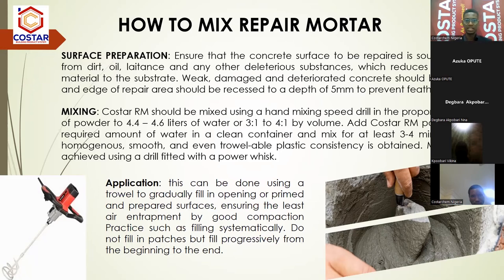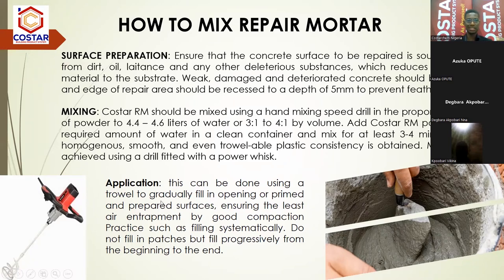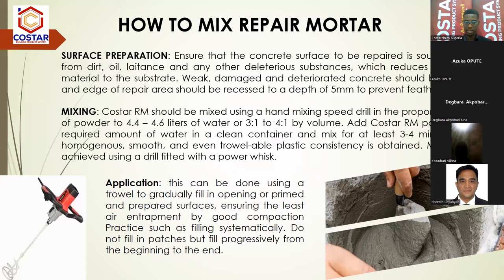For application, use a trowel to gradually fill in the openings after surface preparation and mixing. Ensure there is least air entrapment when filling in these voids to avoid further defects. The patching should be done in a progressive manner — not patching at the center, then up, then down. If you are taking the crack from top to bottom, you follow that line progressively. This helps to reduce the occurrence of air entrapment.